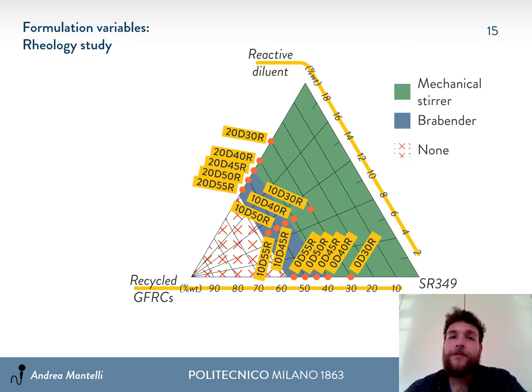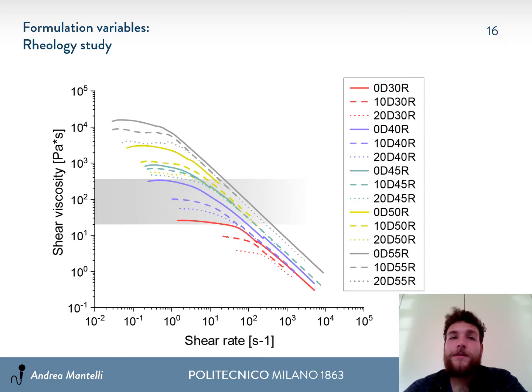Then we selected 15 formulations to test the rheological behavior. And as you can see, all the formulations exhibit a Newtonian behavior at low shear rate and a pseudoplastic behavior at high shear rate. From the experimental data, we have also been able to define a printability window and also to exclude some formulations from the next tests.